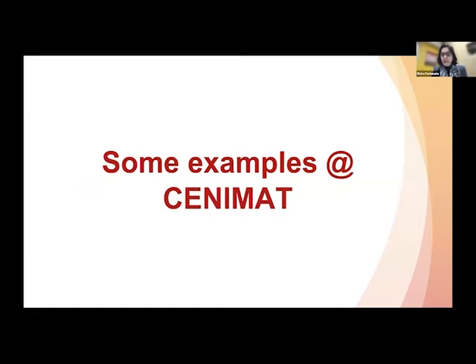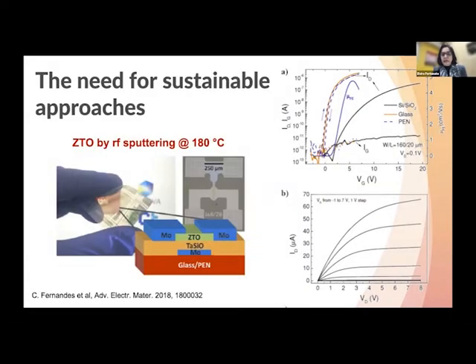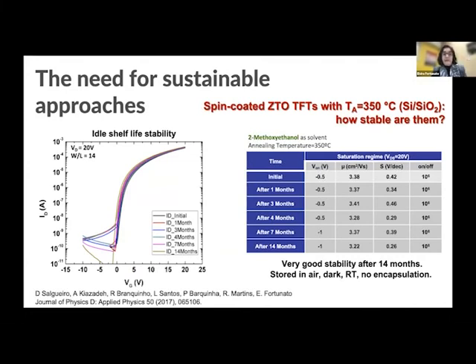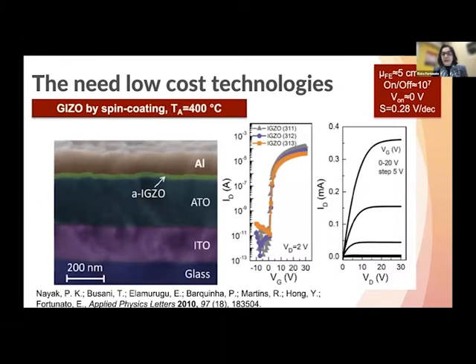So now briefly some examples at our laboratory. Here are examples using ZTO instead of indium gallium zinc oxide. So it is possible to work with sustainable materials for these particular devices. The same, we are able to use a solution process. Here it's an example of some devices using just spin-coated precursors based on ZTO. Also here, at the beginning, we started to mimic a little bit what was done by sputtering with gallium indium zinc oxide, and we succeeded in having similar results using a very low cost technology like spin coating.